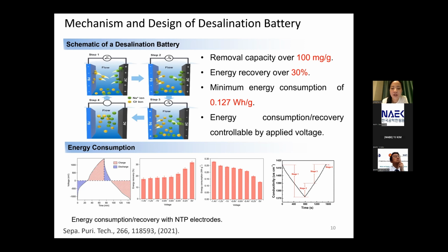After that, we change to step 2, which is our discharge process. In this discharge process, we release the sodium and chloride back into the brine water. Then we go to step 3, and we keep releasing those ions. In that way, we also power some small devices and small equipment, until we reach the all-neutral stage. The AC and Prussian blue analog have both fully released the sodium and chloride ions, which stay hosted in their structure. Then the whole structure goes back to stage 0, and the whole process starts again.